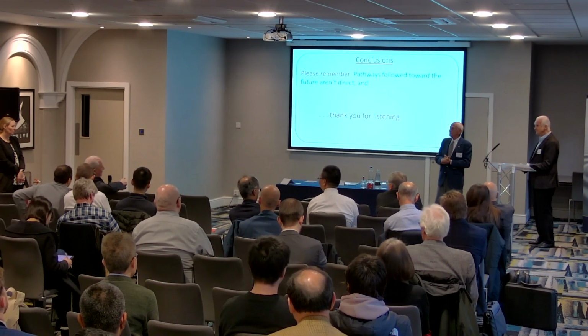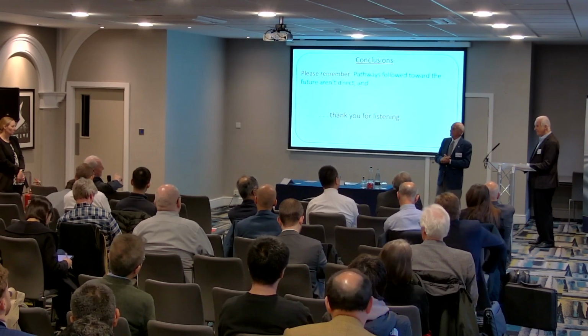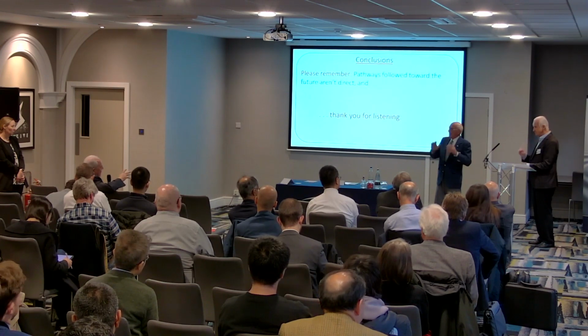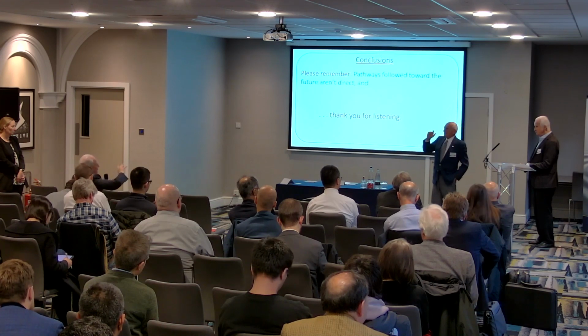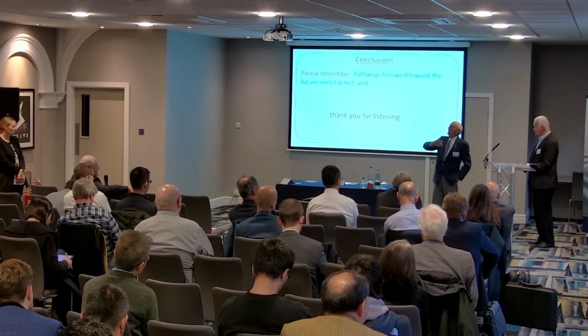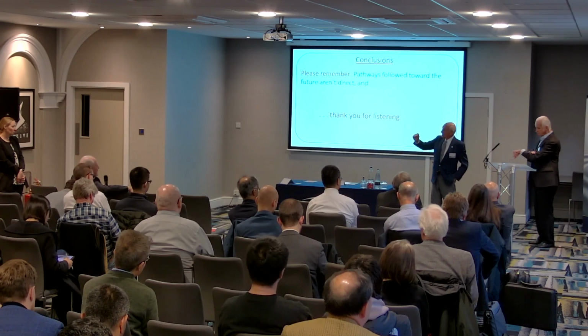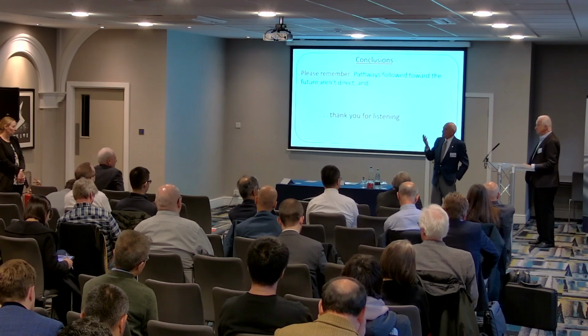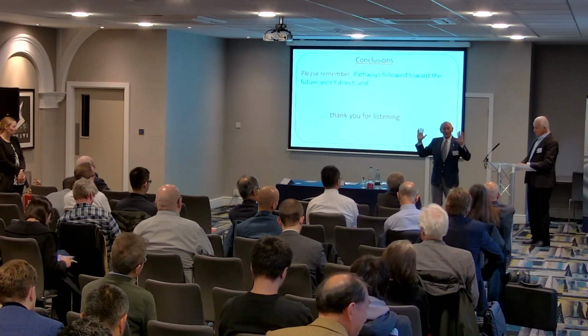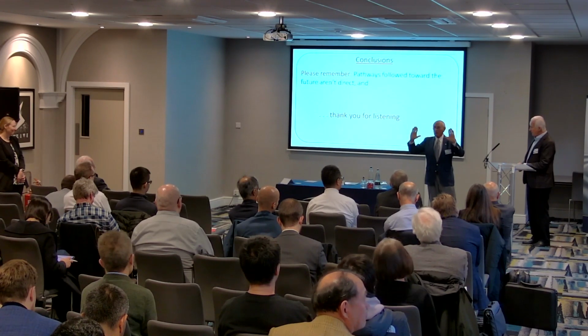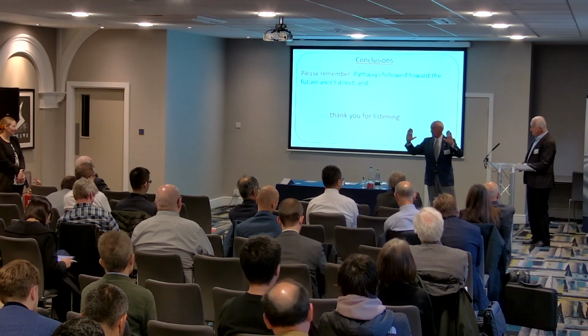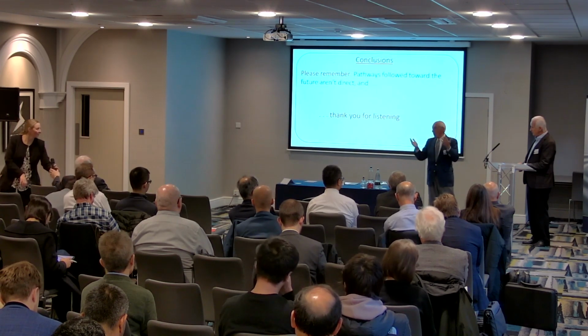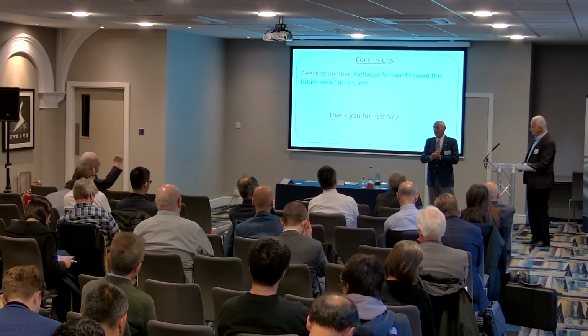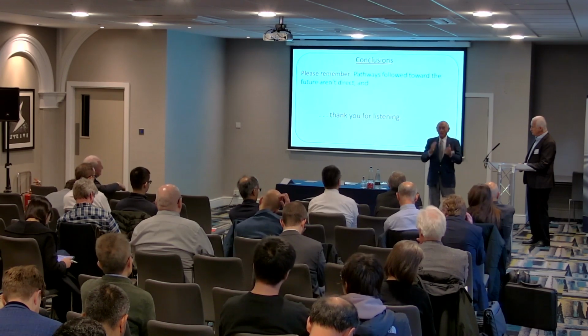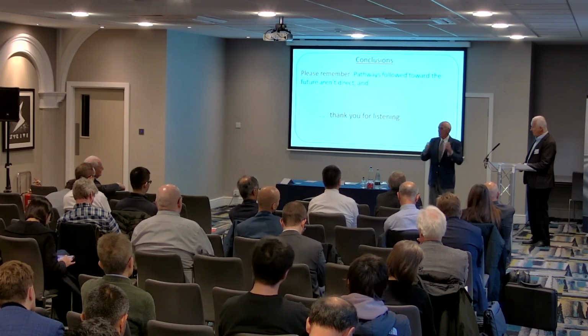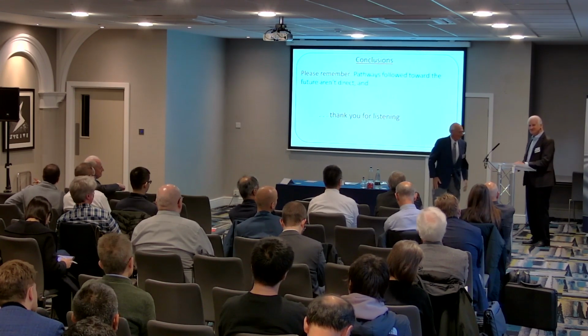Okay. Can I just check, as calculated, the thermal flow is going on to maintain a stable interface shape. It's not changing. There's no evolution of shape. That's a static shape, I think you said. And it's being maintained under the thermal flow. Right. That static shape has a certain curvature gradient or chemical potential gradient, which is demanding that flux flow. So it's part and parcel of the local equilibrium. Now, please remember, those are not equilibrium pictures. When you hold an interface like that stationary, you're generating entropy. So we're not violating anything. But the whole system then is being exposed. And I must say, the new multi-phase field calculations done by my colleagues at Arizona, it's just wonderful to be able to see that and how the heat flow is diverted. Okay, thank you very much.